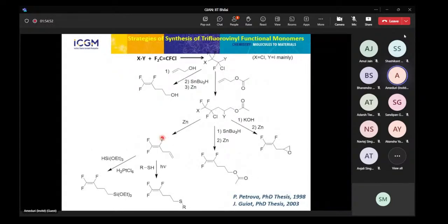So we have been able to prepare also this kind of, this is the Petrova's PhD. It was 20 years ago, 25 years ago. And by addition of ICl onto CTFE, we could prepare some intermediates that require some organic chemistry in order to have a trifluorovinyl hydroxy, trifluorovinyl silane, trifluorovinyl sulfur containing carboxylic acid or alcohol, acetoxy here, epoxide, and a diene. So she made various monomers that we copolymerized with VDF.